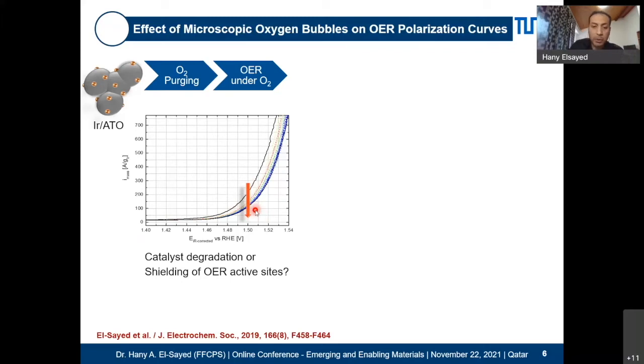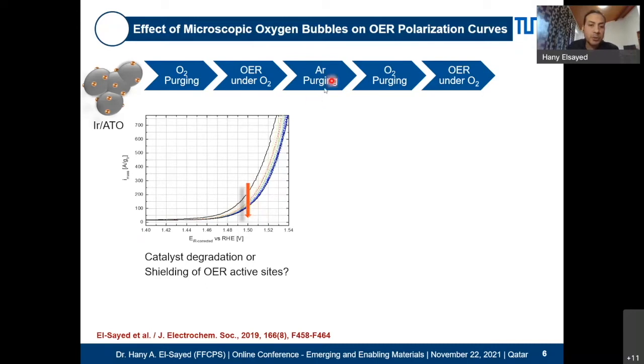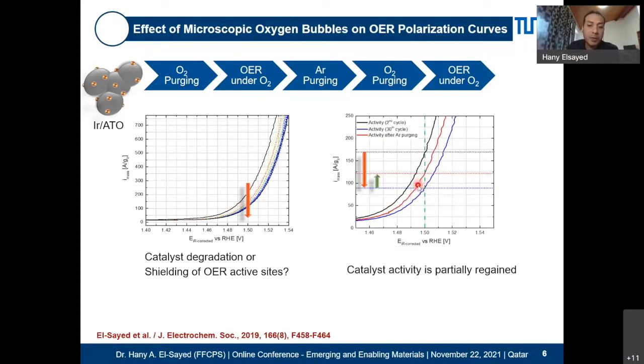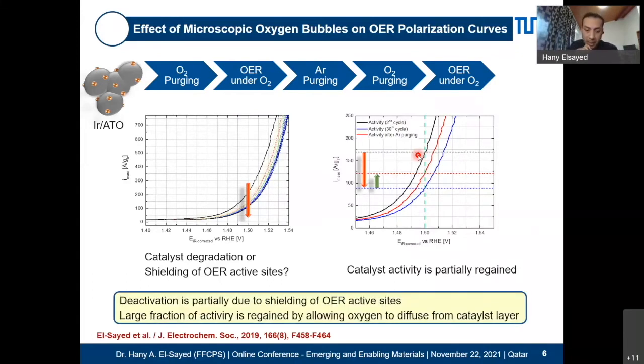But even so, after these 20 cycles, we decided to purge the system with argon. Why? Because we think that the microscopic oxygen bubbles inside will only come out to the electrolyte if we purge with argon and remove the oxygen that is saturating the electrolyte. And this is basically what happened. At the beginning, you have this black curve going from here to here, but after purging with argon, you start the linear polarization again, and then you get a higher current. Where does this come from? You simply emptied out the porosity, or at least partially, of the catalyst layer. This is our very first experiment in this regard.